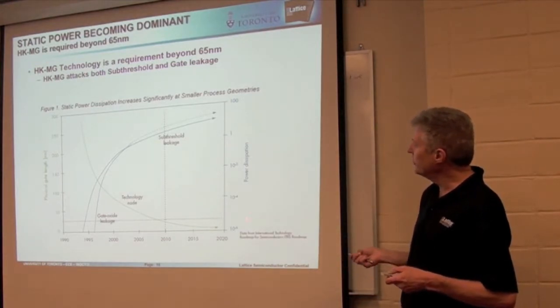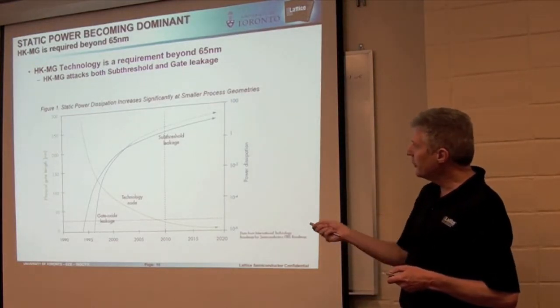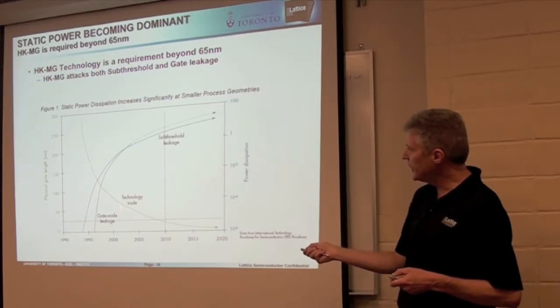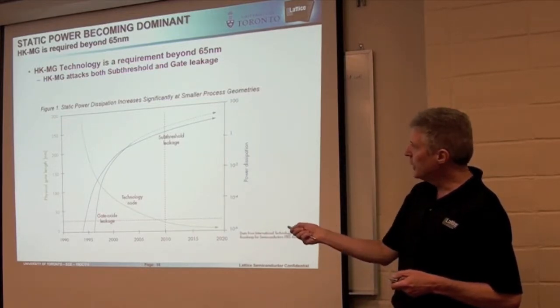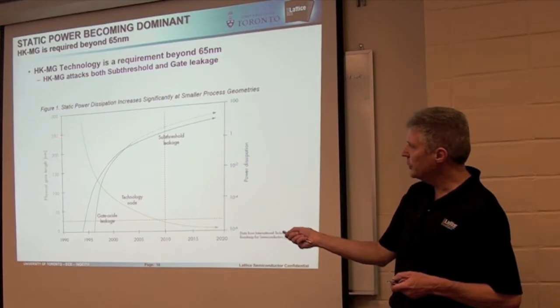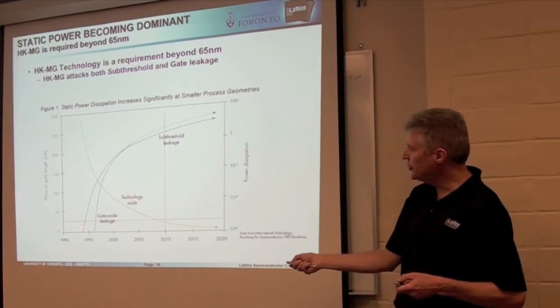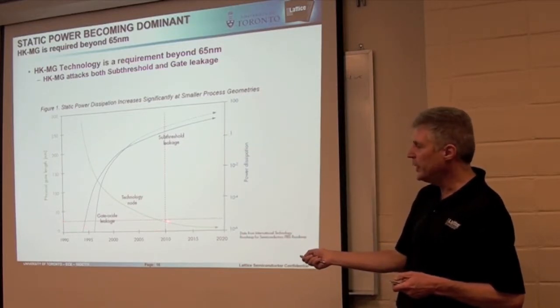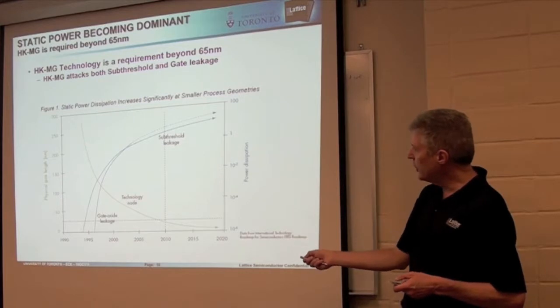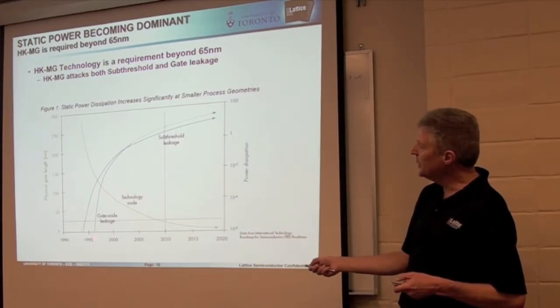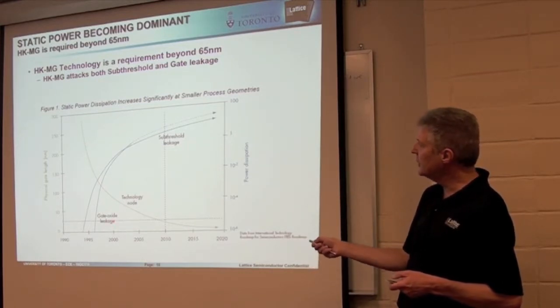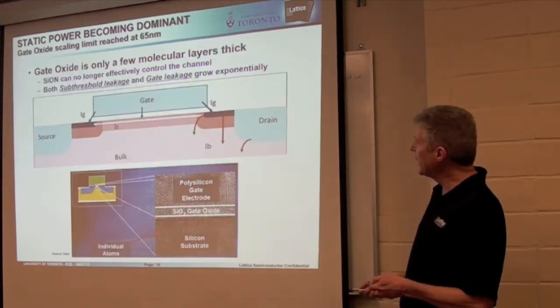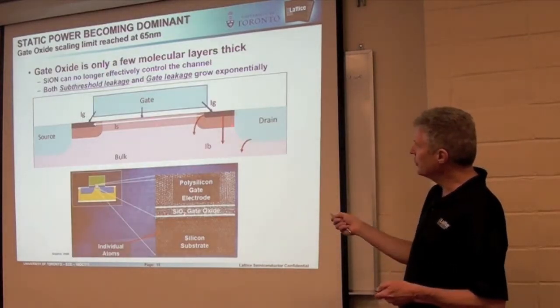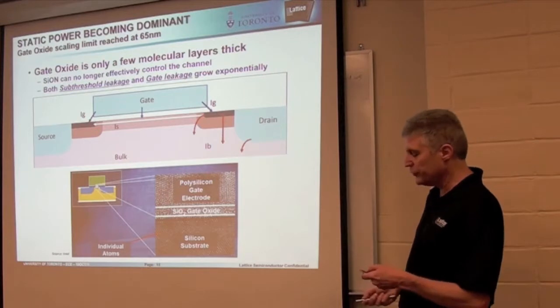And again, this is from the ITRS, and this talks in terms of the green line being the technology trend from quarter micron here. These are feature sizes, 250 nanometers or quarter micron, down to today's region of 32 and 28 nanometers. So you can follow the green line down. And here's two leakage characteristics: gate oxide leakage and subthreshold leakage. Back on the previous page, that's this gate leakage here and the channel leakage here from source to drain.